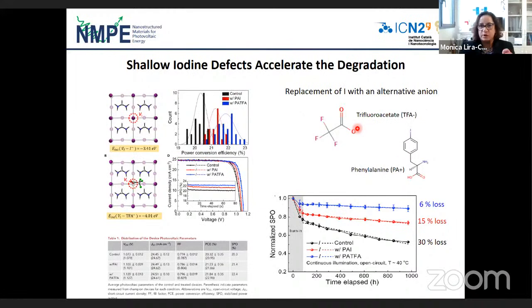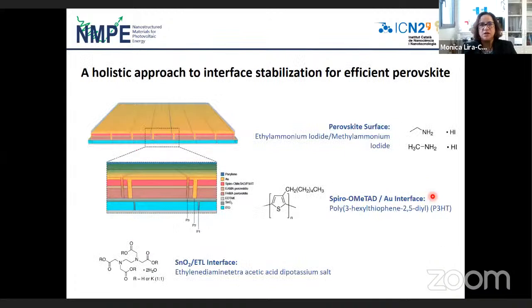So doing this, they were able to see that the efficiency in these solar cells also improves a little bit, not as much as the others we observed, but you can see that the voltage increases and also the efficiency. So they are also passivating deep defects, but here you can see the stability of the solar cell after 1,000 hours is only 6% loss, which is also very, very good. Again, I insist that the shape, size, and type of functional groups are also important for this stability of solar cells.